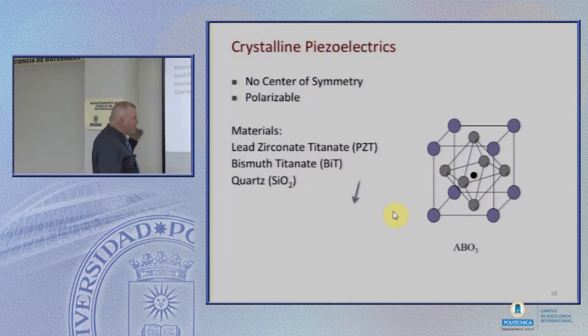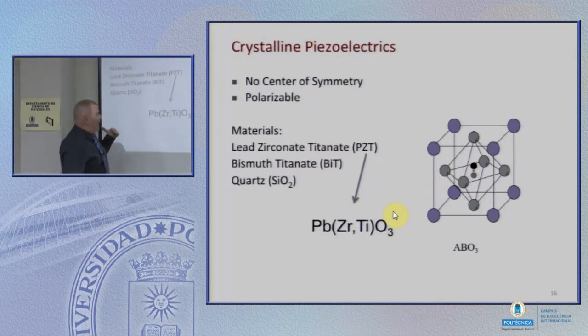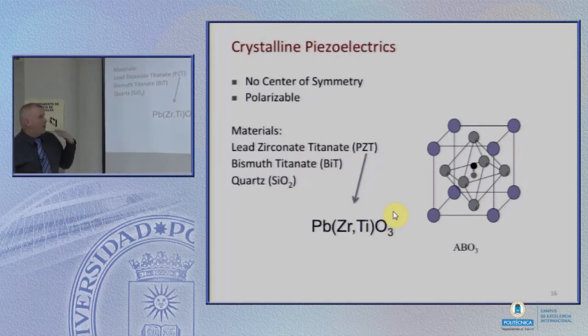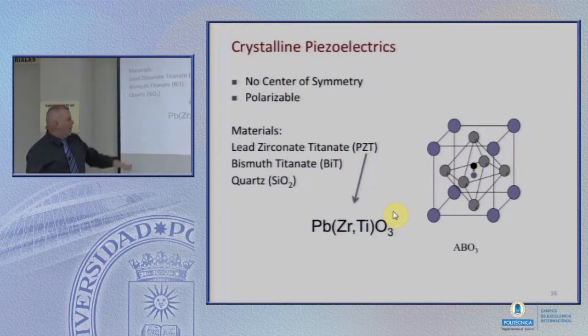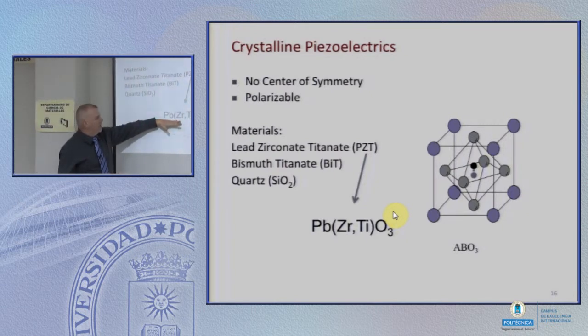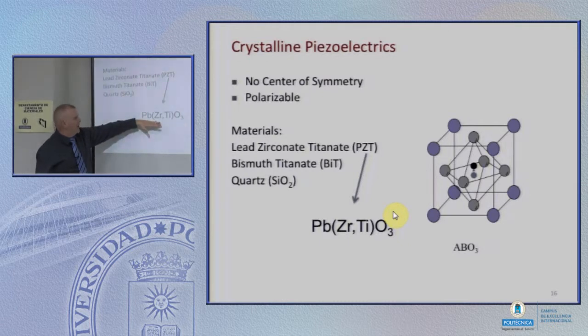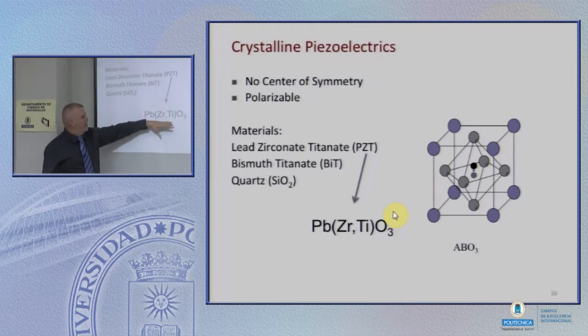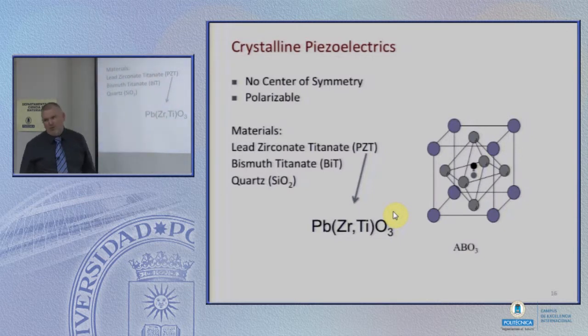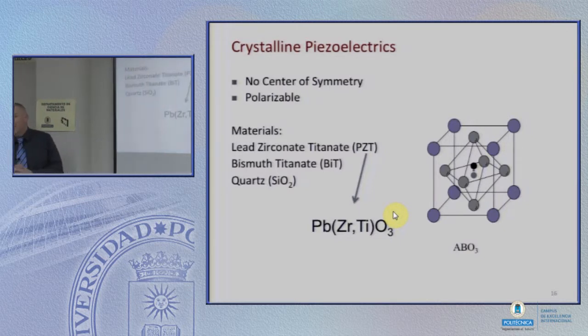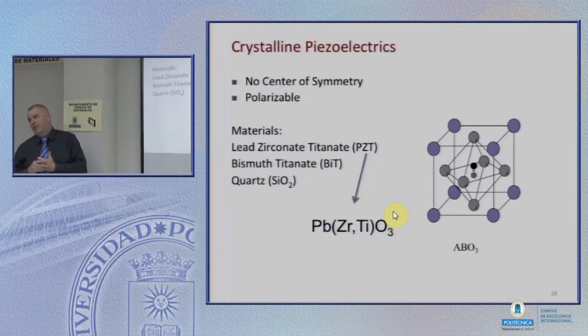But most of the materials that perform really, really well, the materials that have a very strong record, are based on this formula. So they're lead, zirconium, titanium oxides, where it's an alloy of zirconium and titanium. So it's actually PZT. The shorthand for it is called PZT. The lead-containing materials are the ones that perform the best, at least in the neighborhood of room temperature. And that has historically been present.